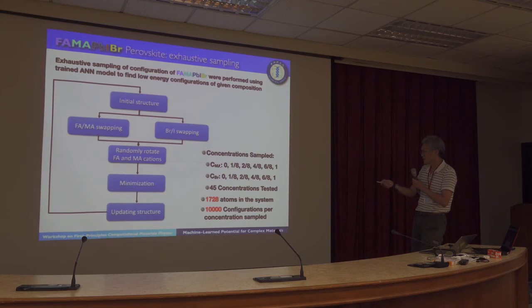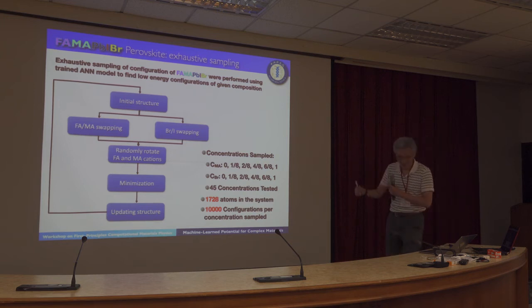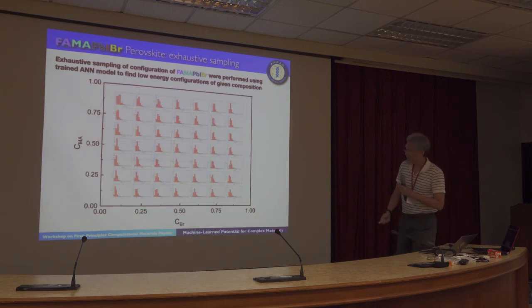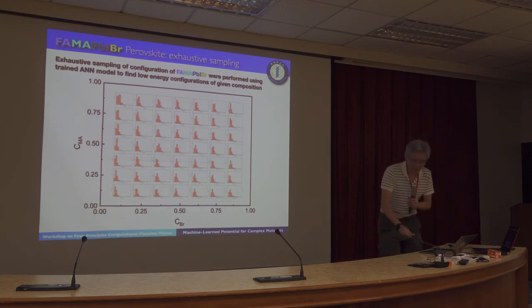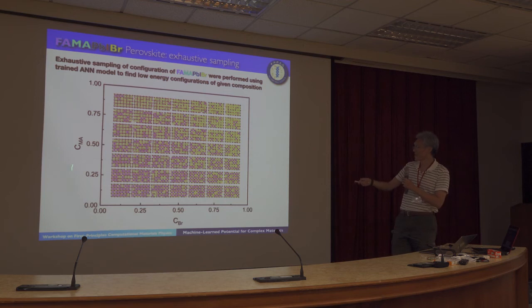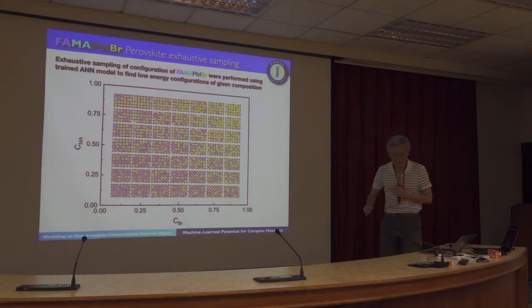And for each concentration, we performed 10,000 Monte Carlo steps. Namely, we sampled 10,000 different possible permutations. And this is a histogram of all the 10,000 structures we have. And if we isolate the structure with the lowest energy, shown here, you cannot really see many things here.